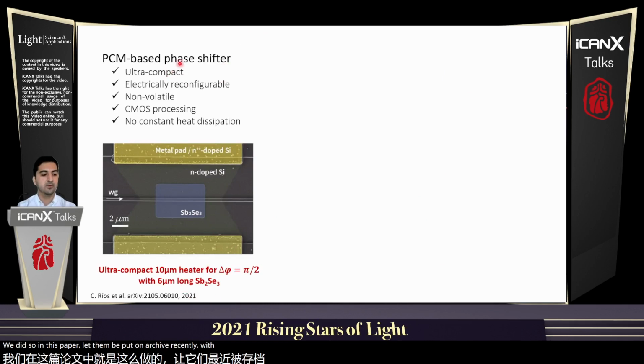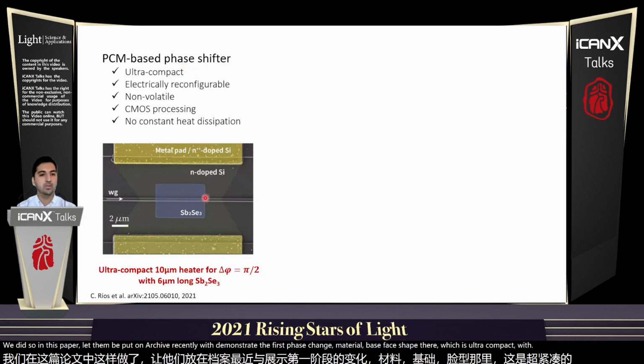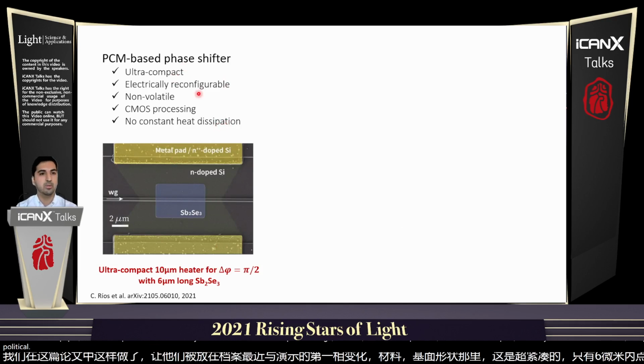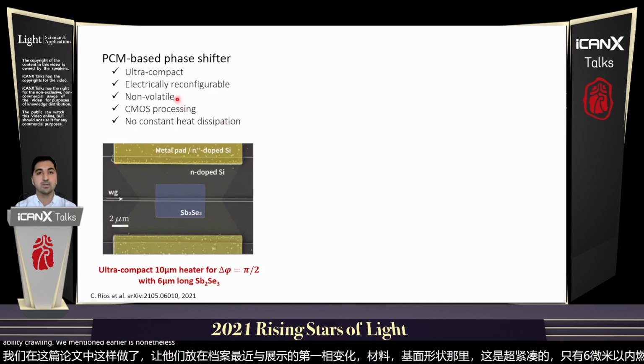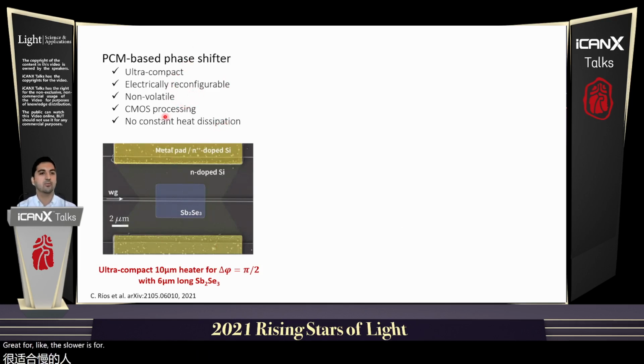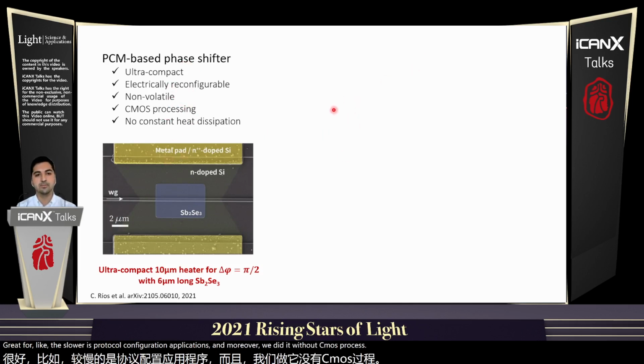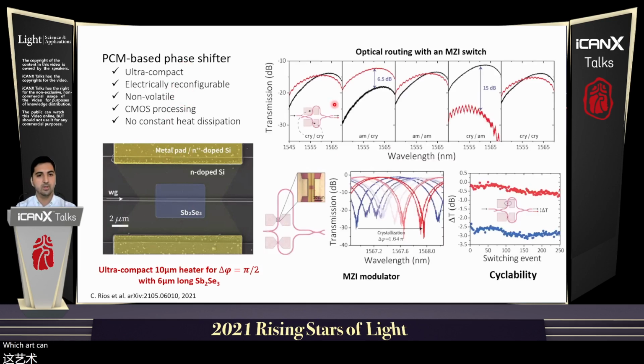We demonstrated the first phase change material-based phase shifter, which is ultra compact at only 6 microns. We achieved a pi/2 phase shift. We can electrically reconfigure it, which solves the scalability problem I mentioned earlier. It's non-volatile, so it's great for slower, sporadic configuration applications. And moreover, we did it with CMOS processing, which shows some of the future in terms of fabricating these devices.